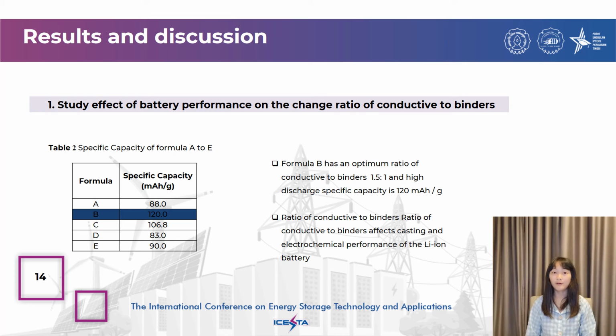Recall that the casting result of formula A has cracking because of minimum binder use with a higher ratio of conductive. It should result in a high specific capacity, but with too high a conductive volume, it results in insufficient mixing and cracking. It can be inferred that the ratio of conductive to binder affects casting and electrochemical performance of the lithium battery. Formula B seems to have the better ratio of conductive and binder for adhesion and electrochemical performance.